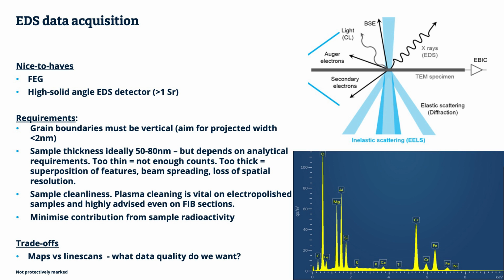With high detection areas come other problems which are more or less well corrected depending on the software that you're using and the manufacturer of the gear. Pulse pileup becomes an issue. You end up with doubling peaks. So the oxygen peak here is huge, as is the aluminium peak. If you're counting quicker than the electronics can cope with, you'll end up with smaller doubling peaks here where 2 coincident photons have not been separated properly by the detection system.